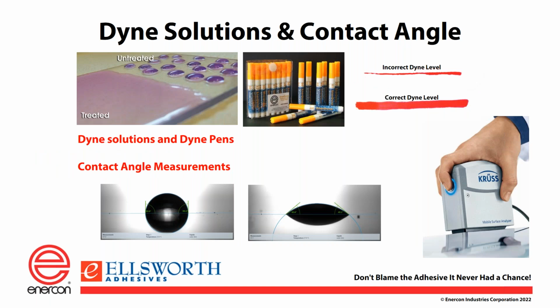So how do we test it? We use dyne solutions and contact angle. Now, when I do dyne, the higher the dyne level, the higher the surface energy. And in general, this is not 100%, but in general, the higher the surface energy, the better your ability to bond to a surface. So again, we use dyne. The range is from around 30 to about 72. The higher you go on the dyne level, the higher your surface energy.